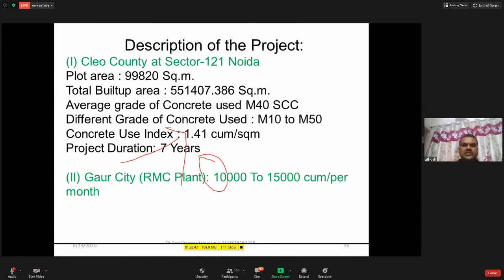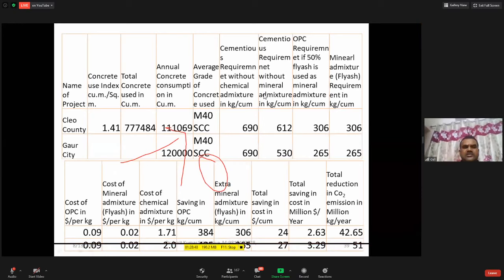Another project we have implemented is the Gaur City Greater Noida West project. As time is less, I am not going to discuss the project descriptions, but here I want to discuss that in the Cleo County project, the concrete use index is 1.41 cubic meters per square meter of the area. I am using M40 self-compacting concrete there. Annual consumption of concrete is about 0.11 million cubic meters per year. And if we don't use any admixtures, the requirement was 690 kg of the cementitious product.